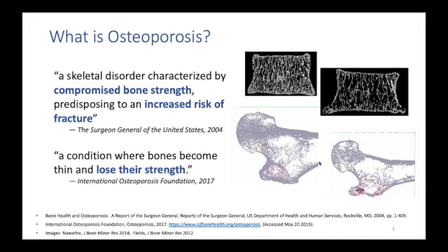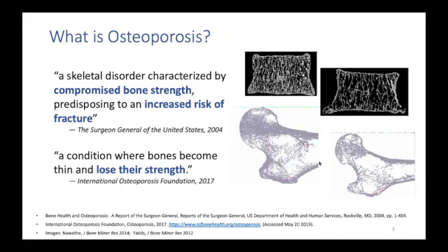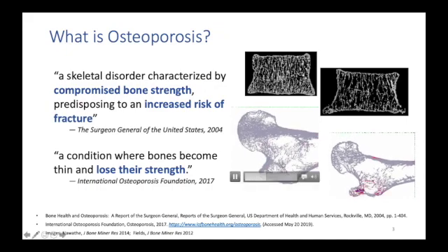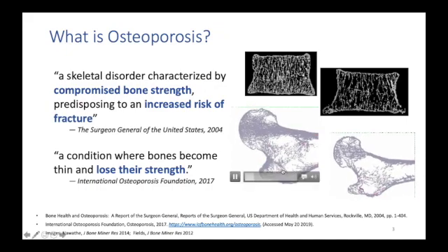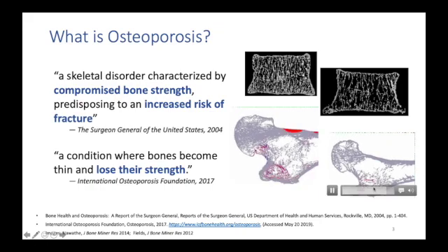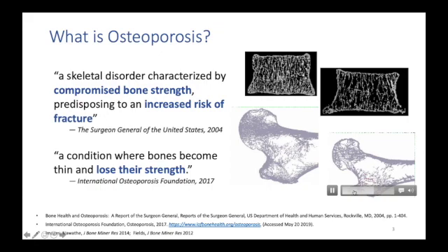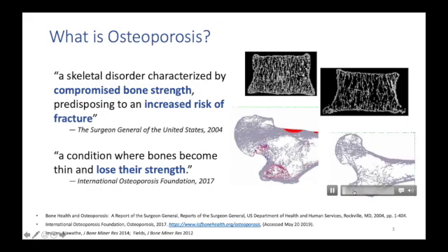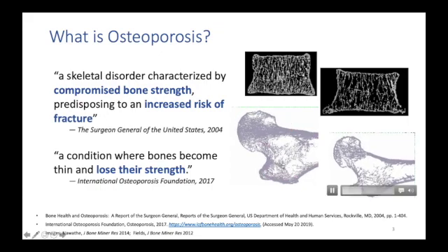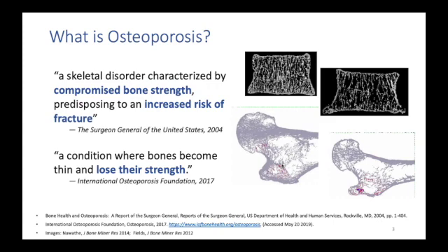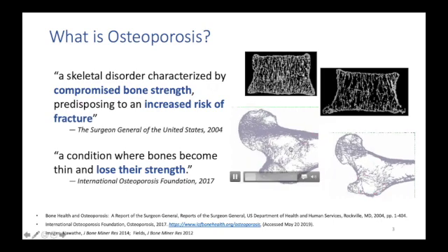It's a nonlinear analysis with material nonlinearity and also geometric nonlinearity. If you look in the trochanter region closely, on the bottom right-hand image, you'll see there's buckling going on of some of the trabeculae. So these computer simulations, very few people in the world can do these because of the numerical complexity. We use Unique's parallelized code to do this.